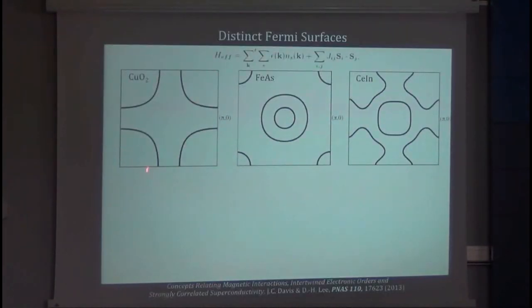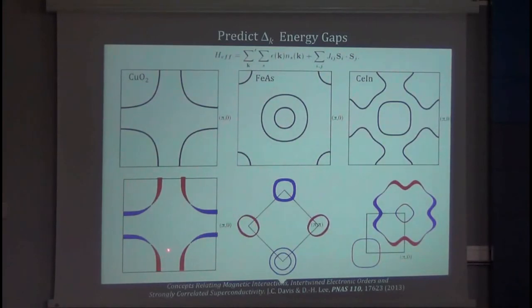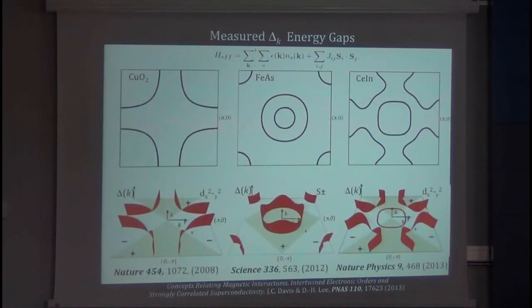Okay, so here are the distinct Fermi surfaces, and here's the Hamiltonian. It looks the same, but it's actually different for each of them because the details of the Fermi surface are different in each case. The details of the magnetism are different in each case. From this Hamiltonian, one can predict immediately the symmetry of the dominant superconducting order parameters which should exist in these classes of compounds. They're only coming from the Fermi surface geometry and the magnetism. Those are the predictions. They're in excellent agreement with the three classes of energy gaps which have been discovered for these three classes of compounds.